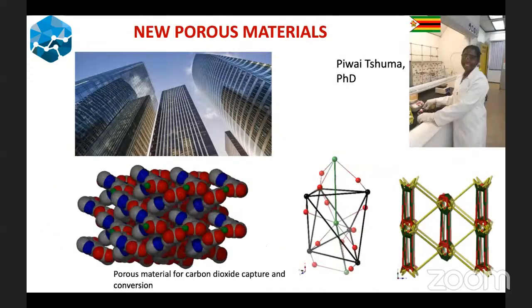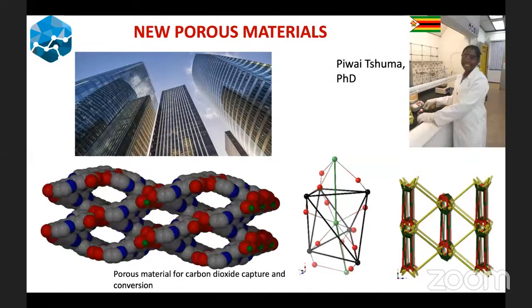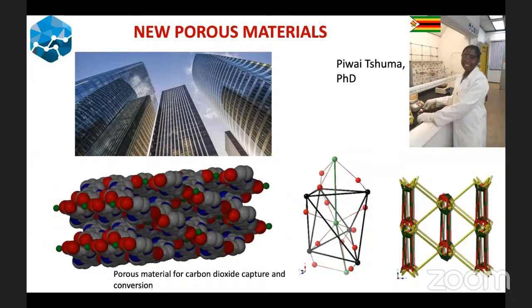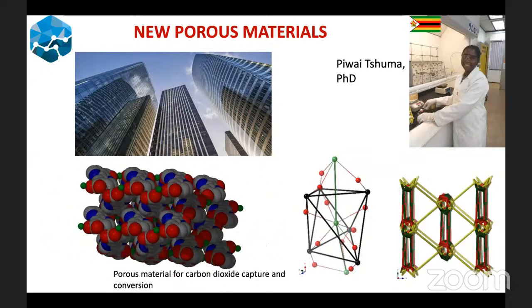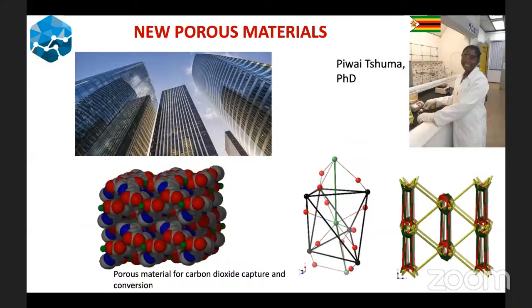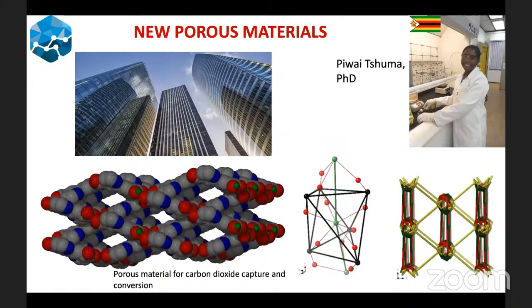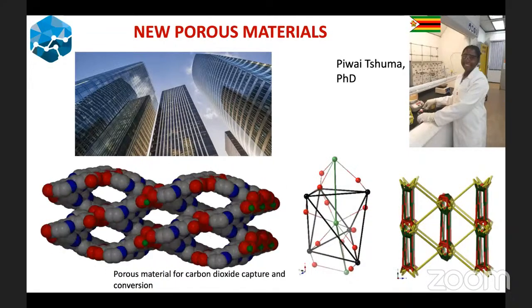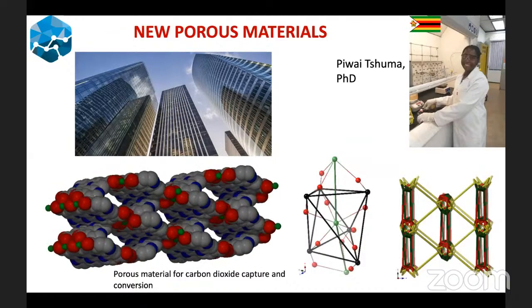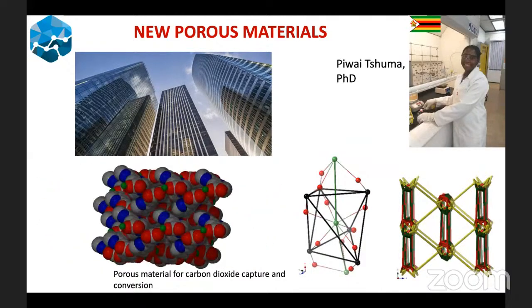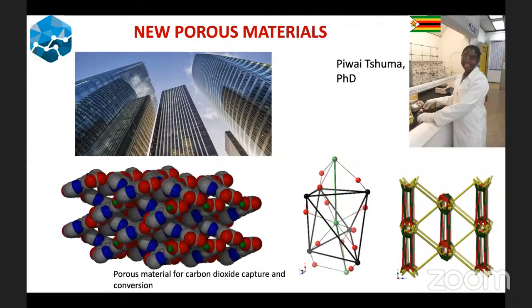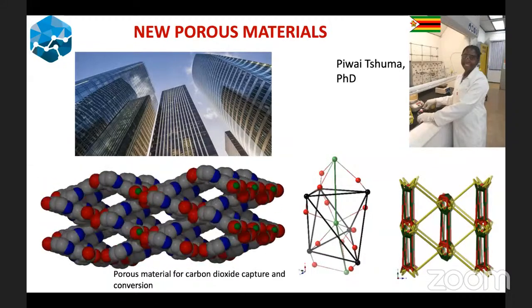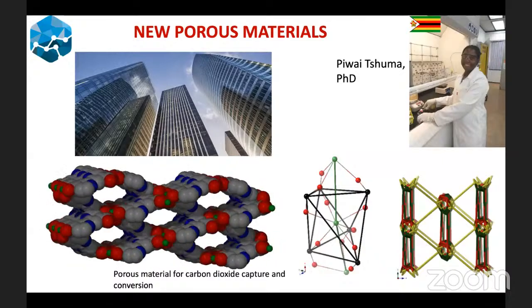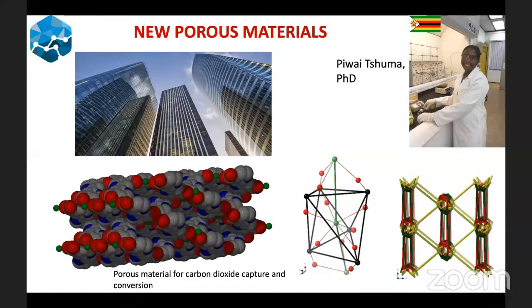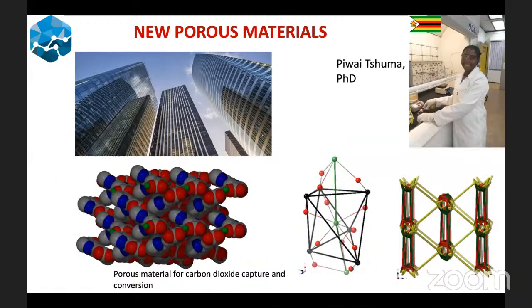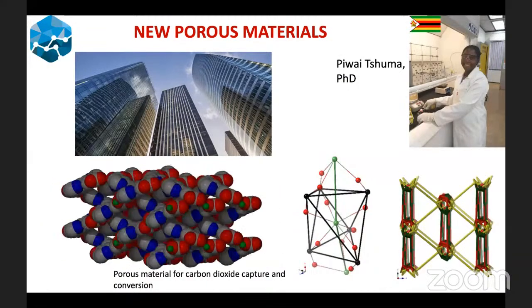But the challenge with these materials is that because they were made at room temperature, when we apply high temperature or when we want to try catalysis, they tend to dissolve, which is not very useful for heterogeneous catalysis, because during heterogeneous catalysis, you don't expect your metal organic frameworks to dissolve. These ones dissolve primarily because the reaction took so long, about 30 to 60 days, and of course, it was done at room temperature.